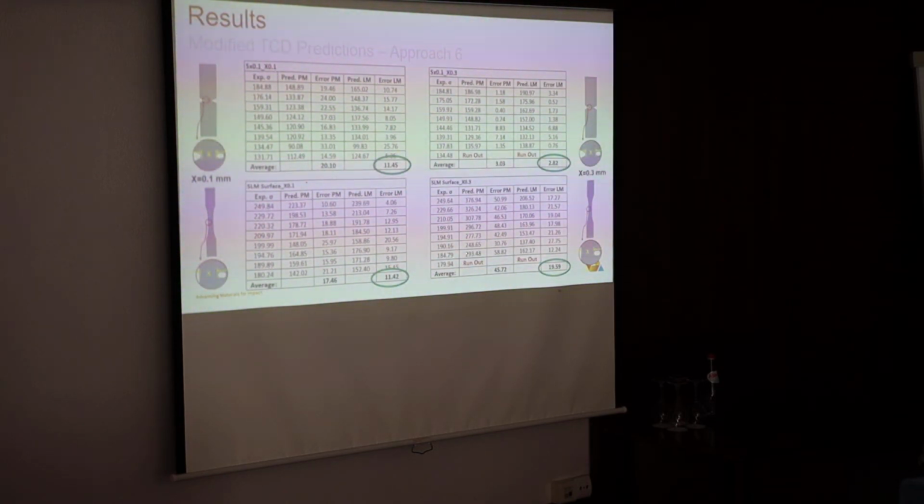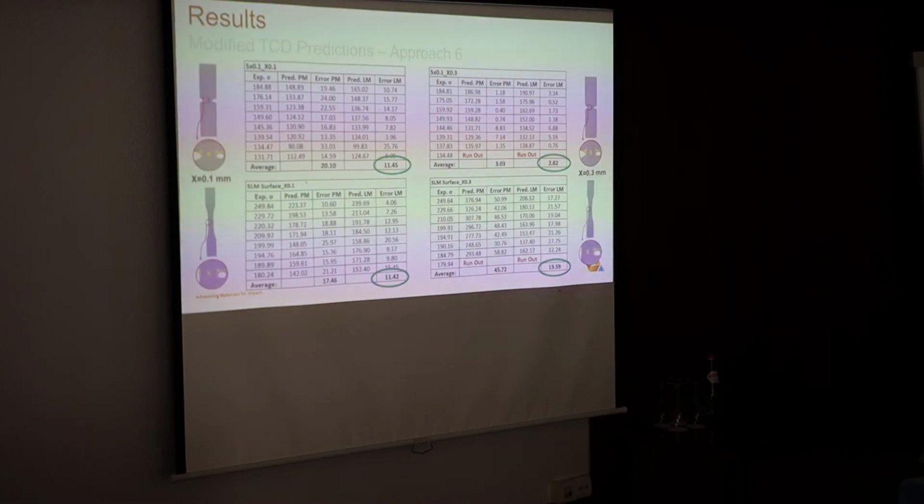These are the results here, whereby we can see that for each of these specimens which we have implemented, the error margins fall within 20%, which is generally considered to be somewhat acceptable in the field of making fatigue-based predictions. Although it must be said, some are a lot more accurate than others, and the model overall would require a lot more work going forward in order to improve it and analyze this data even further.